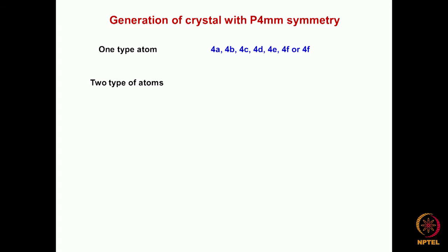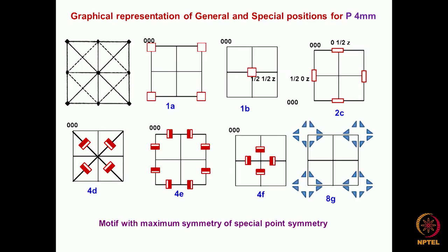Suppose you assume that two types of atoms are present, atoms A and B, and the stoichiometry is AB. If we fill all the A positions with this particular type of atom, on the lattice positions, then what option does B have? Since the stoichiometry is being maintained, if it comes to this particular site, the number of atoms per unit cell for both of them is 1. This is the only option which is available. It will choose that position.